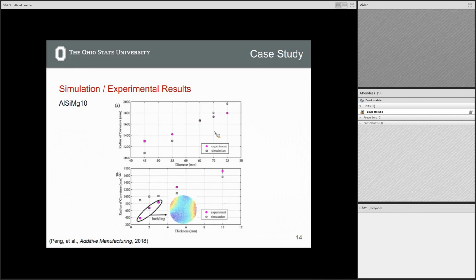So this is as we vary the diameter. We hold constant the 5 millimeter height of that disc, and now we vary the diameter. This is what we tested a bunch of right here. And then these are our different treatments for aluminum, showing pretty good correspondence here. And then this is varying the thickness.